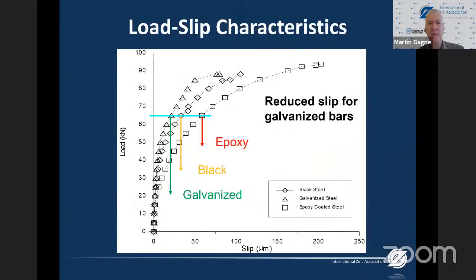A similar test, but on a different sample. Here we took concrete beams and we bent them in a 3-point bend test, and we measured the slip, how far the rebar moves within the concrete beam. So we can see at a given stress level, and here I put the blue bar at 65 kilonewtons, the galvanized rebar has the least amount of slip, followed by the black bar, and then the epoxy coated bar has the most amount of slip.